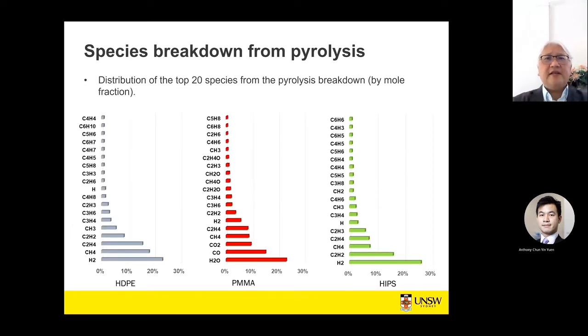This slide here just shows you a breakdown of all the compounds that were derived from the MD simulation itself. What we can do with this data now is use it as the fuel for the combustibility of polymers. Because in actual fact, the cone calorimeter is unable to get down to this fundamental level to obtain the species that constitute the burning of polymer. Molecular dynamics offers you this avenue. And now we know what compounds will contribute to the combustion, and we can feed all these compounds into the CFD model.